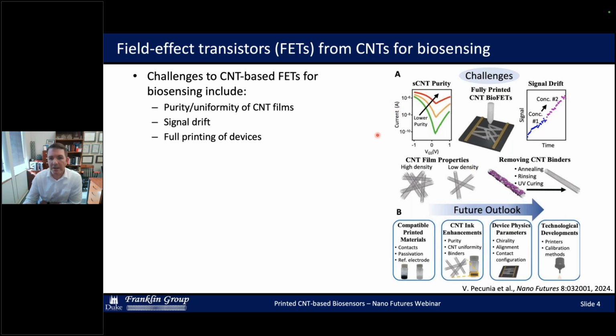And this includes getting to a point where we have better reproducibility or consistency in the devices. Utilizing printed thin films of nanotubes actually does aid this particular challenge in a significant way. A tangled network of nanotubes across a reasonably wide width of a device actually does produce a reasonable amount of consistency from device to device compared to, say, just a few nanotubes that are attempted to be isolated into a transistor channel. But there's work that remains.